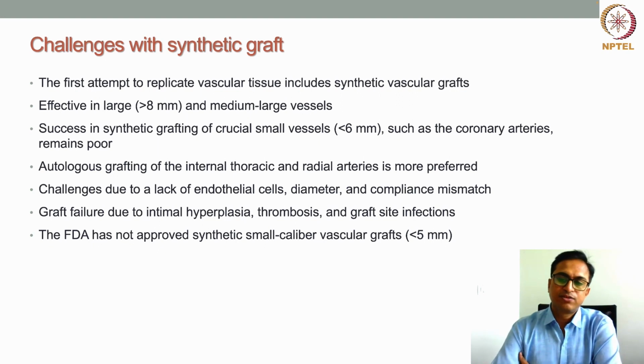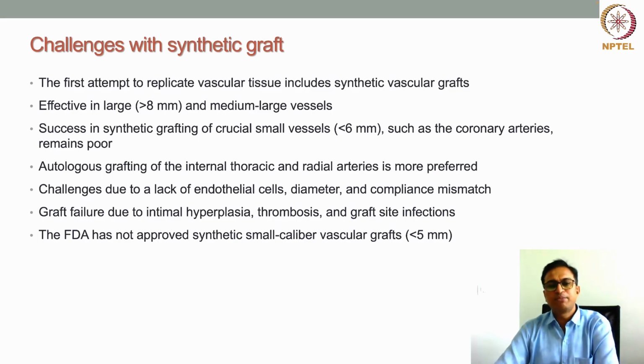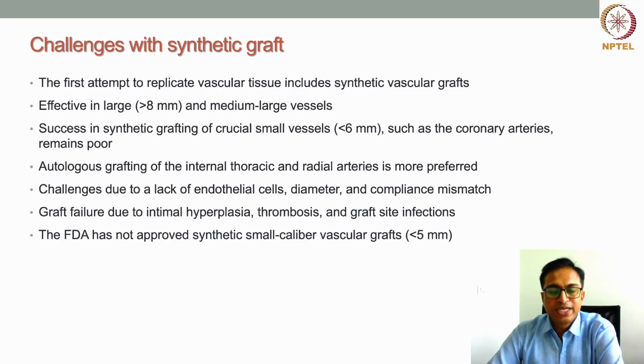That is why it's really challenging to bioprint smaller diameter blood vessels. In most cases, small diameter blood vessels developed with synthetic materials fail in the clinical setting because of intimal hyperplasia, which is overgrowth of tissue, or thrombosis, a blood clot within the graft, or graft site infections.